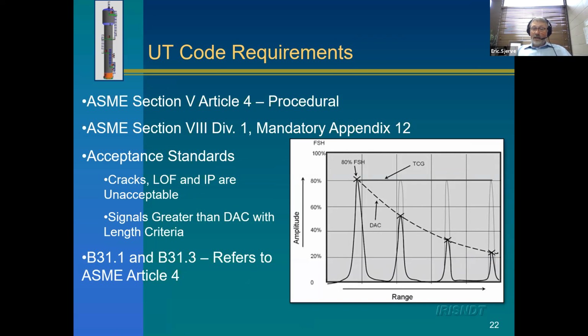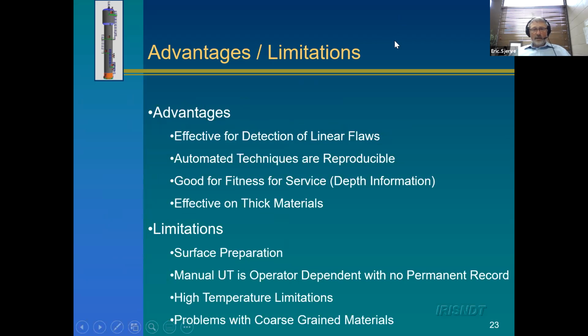And then we set that DAC at different depths. So this would be close to the probe, so the sound pressure's high. And then as your sound attenuates, you have to set a DAC that's lower because, as I said, the deeper into the material you go, the more your sound dissipates. So you set a curve that represents how much sound amplitude that 3mm side drilled hole reflects at different depths. And you compare all your defects to that. So if you have a volumetric defect like porosity, and it produces more reflected energy than this DAC curve, then it's rejectable. If it produces less than that DAC curve, it's acceptable. That's what that means. So I hope that answered the question. I guess it's hard with Zoom to know, but hopefully that answered the question.